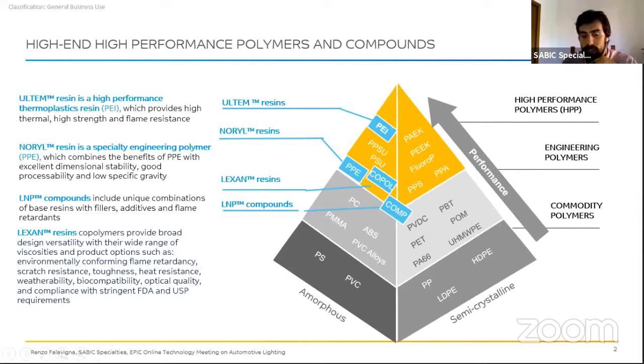Here you have an overview of the resins that we can propose. So starting from our best-in-class material, ULTEM. ULTEM is a polyetherimide, so highly transparent for high temperature applications. It was widely used for auto lighting in the past. Then we have Noryl. Noryl is a PPO resin, so it's mainly commercialized as a blend between PPE and polystyrene, but can also be polyphenylene oxide, PPE, plus polyamide. And it's well known because of the low density and high mechanical properties. Then we have a full range of compounds where we use our resin we produce, or we compound resin from other sources. So we don't produce, for example, polyamide internally, but we use polyamide in our LNP compounds.